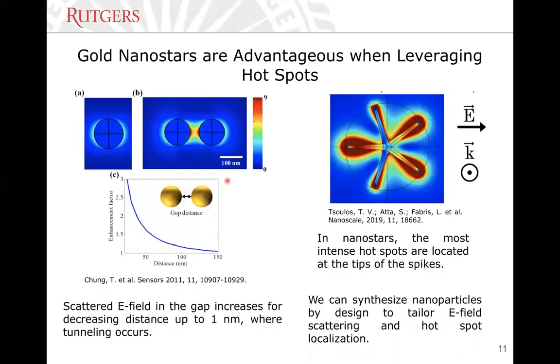And so as I was saying, we know that when we have spherical nanoparticles, if we bring the 2 nanoparticles together, up to 1 nanometer gap size, we see substantial enhancement at the gap. We cannot go below 1 nanometer because then we start having electron tunneling effects. But at these levels of separation, we have high enhancement, which then tapers down at larger separations. However, if you do try to synthesize these particles, then you realize that it's not as straightforward.